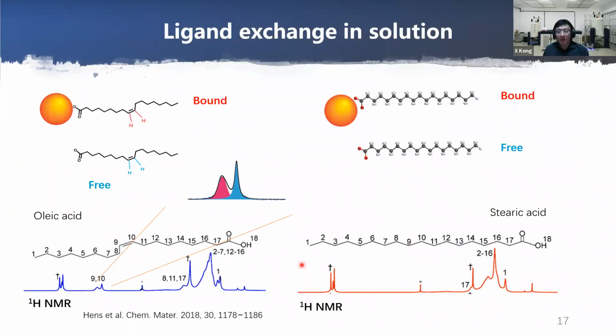So the second part of our study is trying to calibrate the ligand exchange on nanocrystals in solution. So when the nanocrystals are in solution, the surface ligands are in dynamic equilibrium of the bound and free states. The bound and free ligands are in constant exchange with each other. So to monitor the exchange, the first step is to separate their signals in solution. Previously, this was done with ligands with a double bond, because the double bond will show a difference in chemical shift when it is bound on the nanocrystal or when it is free in solution, like here, the red and the blue color.